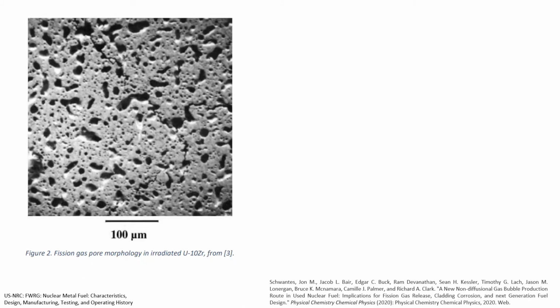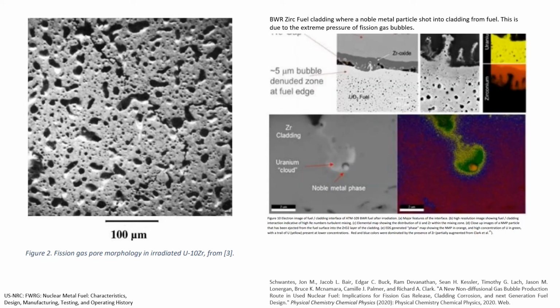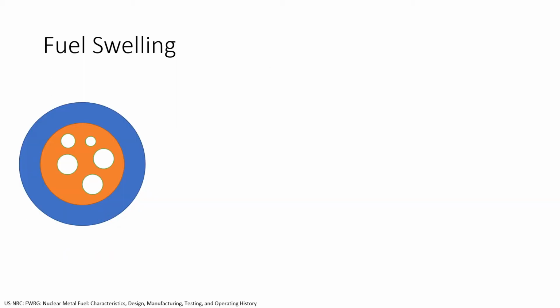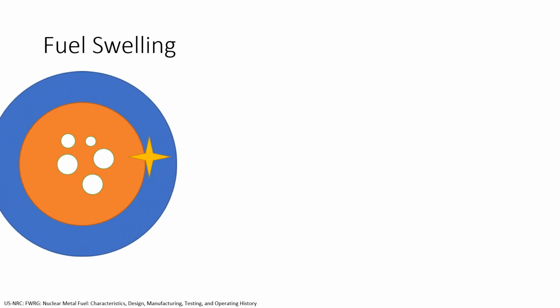Xenon, krypton, and helium are of major concern. These bubbles can form extremely high pressures on the order of gigapascals. If near the edge of the fuel pin, bubbles will either leak or, under some circumstances, explode, sending metallic particles into the fuel cladding. Insoluble gases under extremely high pressures cause mechanical strain. Radiation-induced strain is called fuel swelling. Swelling is actually strong enough to burst fuel cladding, and it is the limiting factor for fuel, until advances in optimizing smear density are eliminating swelling failure as being the primary mechanism for fuel failure.